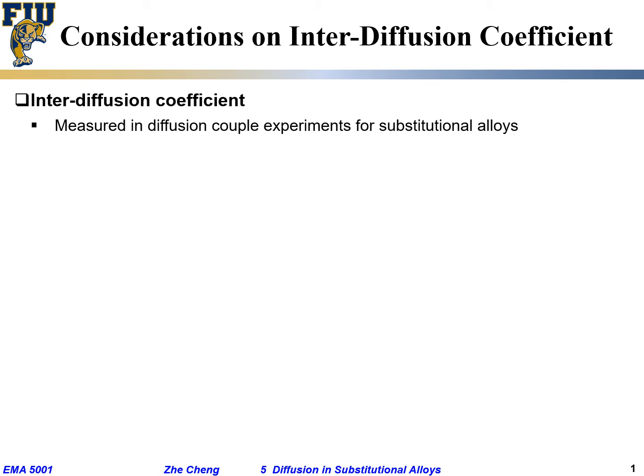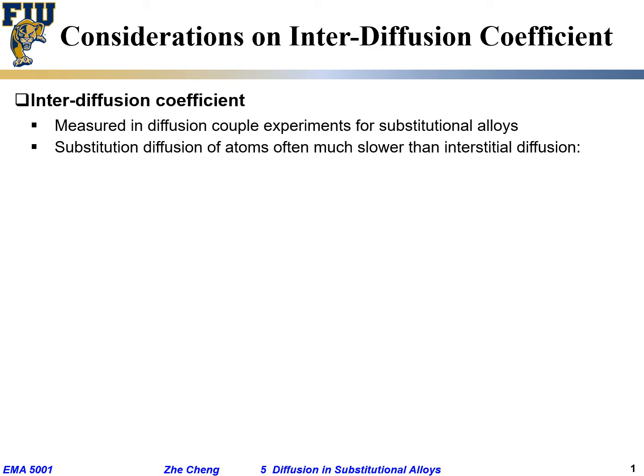Putting copper and brass together, or putting some other materials together. The so-called substitutional diffusion is often naturally much slower than interstitial diffusion, because it really takes time for the vacancy to re-equilibrate, to find a vacancy nearby. And how fast? We give one example.